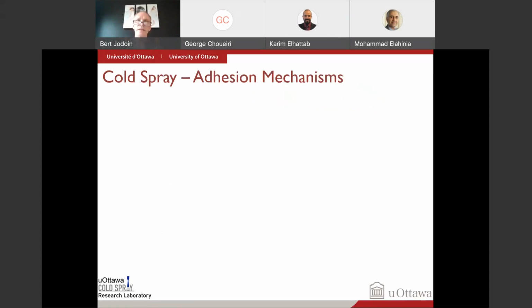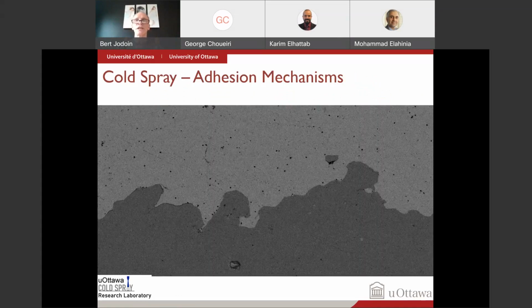So the first one, the adhesion mechanism. Well, there are two adhesion mechanisms. The first one is what we call mechanical anchoring. If you have here at the bottom the top of the part that you want to coat, you can grit blast it hard enough so that you create this intricate topology. When the particles that you project hit the surface, they're going to deform, and they're going to basically do just like a Velcro effect and become attached to this intricate topology.